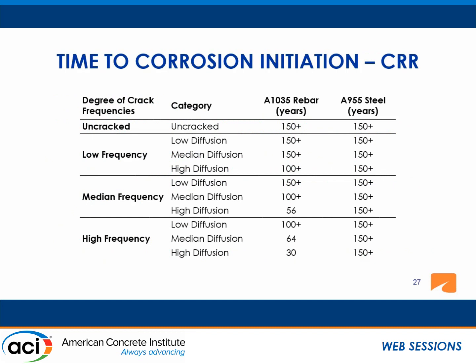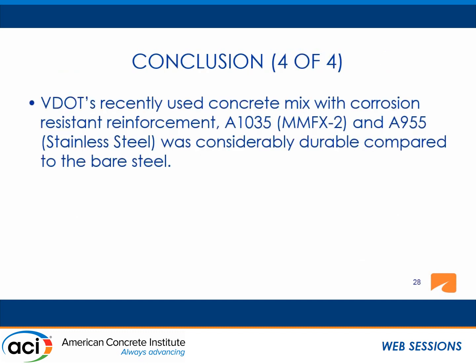The results showed that for stainless steel, it doesn't matter how much the deck cracks, the corrosion did not initiate for 150 years. However, for the 1035, if there's enough cracking and an adequate amount of chloride diffusion, the corrosion initiation may happen at 30 years. So that's our final conclusion. We found that even though there are differences between the corrosion-resistant reinforcements, these perform way better than the bare reinforcement that we used to use before.